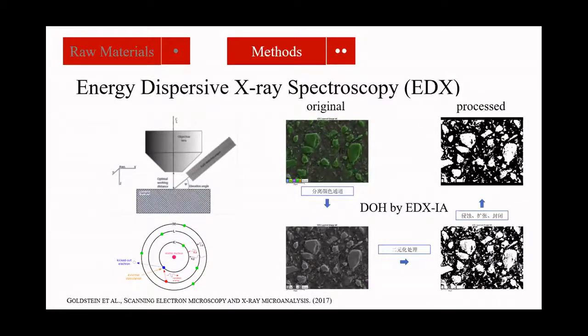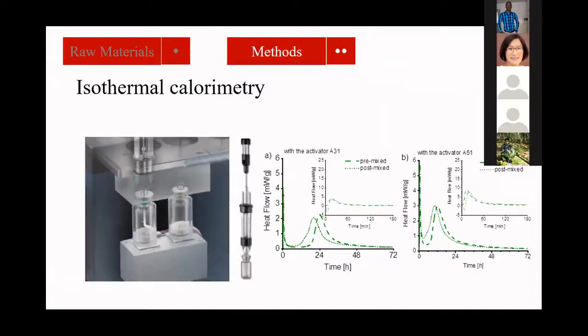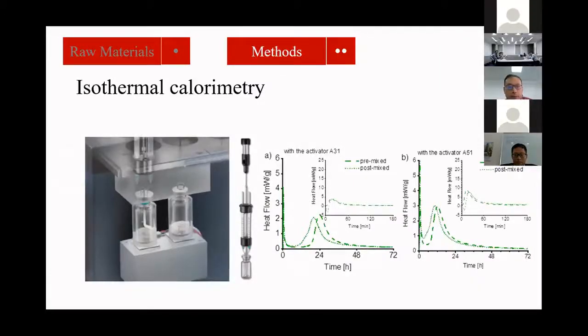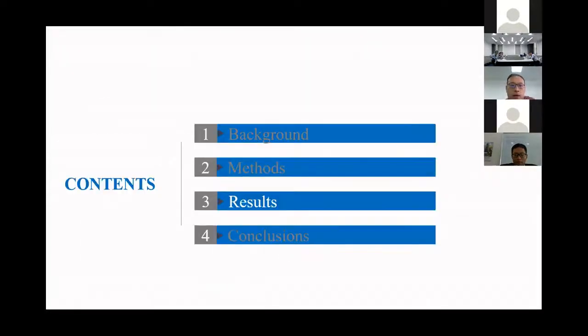In this research, I also use energy dispersive X-ray spectroscopy to determine the elemental mapping or elemental distribution in the alkali activated materials, and coupled with some image processing, we can determine the degree of hydration, for example, of slags in this case. For its reactivity, we all know that isothermal calorimetry is a good method, and it can be used to indicate the reactivity, especially the reaction kinetics. And in this study, I use the cumulative heat as an index to evaluate the reactivity of SCM in a given time duration. Now I will go to my results.